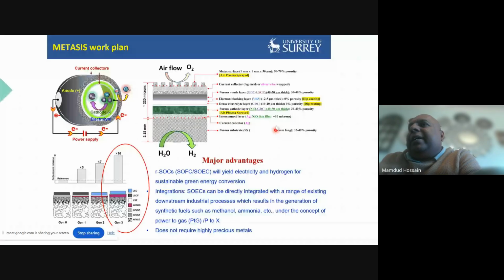So our thickness is actually 2 micron, 3 micron, 5 micron, 40 to 50 micron. We don't need 400, 500 micron or 1 millimeter thick cathode and anode anymore, because these are all supported on that structure. Number one. Number two, we have a balance of porosity, and we have a multi-layered cathode and multi-layered anode, which is made of nickel oxide GDC, then GDC, then YSZ. So you have different combinations of electrolyte and cathode material. In some cases we also had another layer of nickel oxide with YSZ and things like that. So we played with different multi-layer structures, different porosity, different thickness, but our advantage is that we put everything on a support structure.